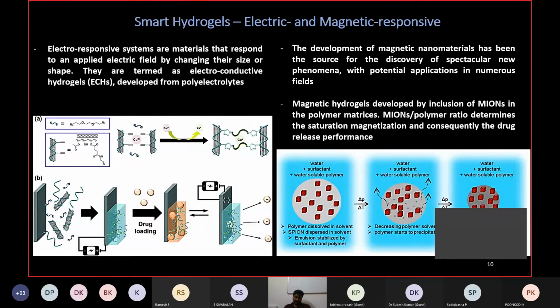One day you come and say you use them as a nanoparticle and this polymer as just the coating polymer, and you call it a magnetic nanoparticle. The other day you come and say it is a hydrogel and you put that magnetic nanoparticle inside. Why these different terminologies, you may ask? Here the composition is mainly the polymer and you exploit mainly the property of the polymer, and these magnetic nanoparticles are just additives. They are occupying the space of the polymer.